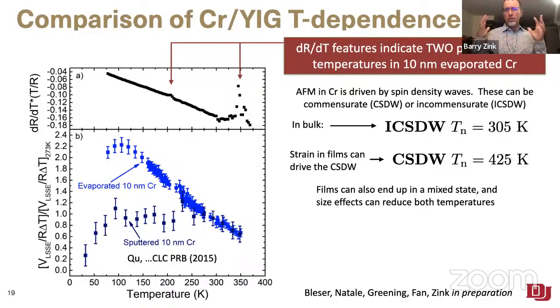But it turns out, even if you have a giant chunk of chromium, you go stick it in and do neutron scattering on it or something, if you strain it, the incommensurate spin density wave collapses into a commensurate spin density wave. That commensurate spin density wave state actually has a higher Néel temperature than the unstrained chromium did. So that's 425. Now that's all in bulk. What happens in thin films? A mess of different stuff happens when you go from bulk to thin films.